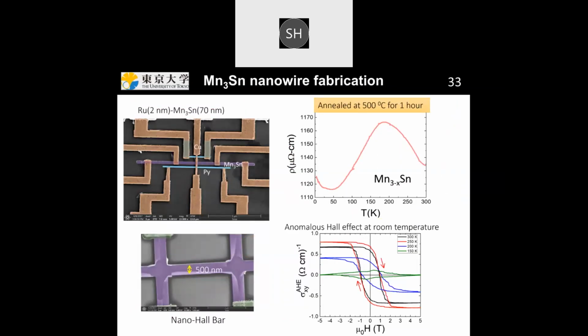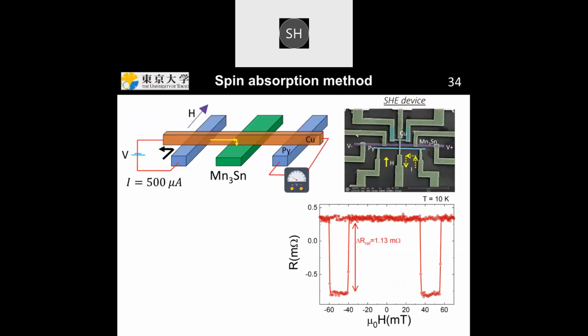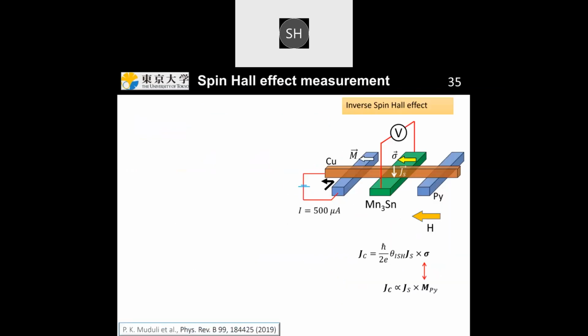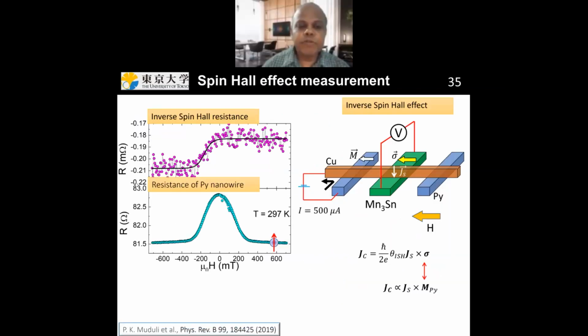So do you think your crystal could behave like this, or does it not have any direction dependence? Yeah, this is a good question. In our experiment, we could see some experimental evidence. For example, you can see that the experimental data is not symmetric around the origin. At zero magnetic field, the magnetization spin polarization direction is along this long axis. So at zero magnetic field, you should not get any inverse spin Hall signal at all, if you assume that this relation is valid: spin current, spin polarization direction, and charge current have to be mutually orthogonal. But this doesn't happen here.